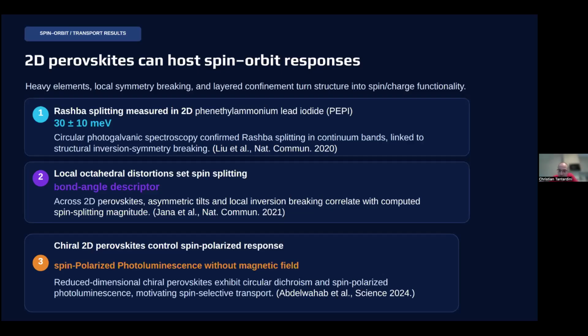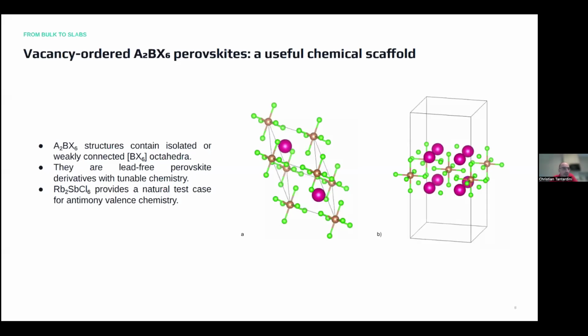So for this reason, it seems that 2D perovskites should be interesting to study. Specifically, we can think of this kind of perovskite written like A2BX6. In this case, these are interesting chemical scaffolds where we have these BX6 octahedra. They can be lead-free, and one of these, which is actually the object of our study, is rubidium-2, antimony, and chloride-6. Antimony is better than lead, but of course it is not the greenest that we can think of.